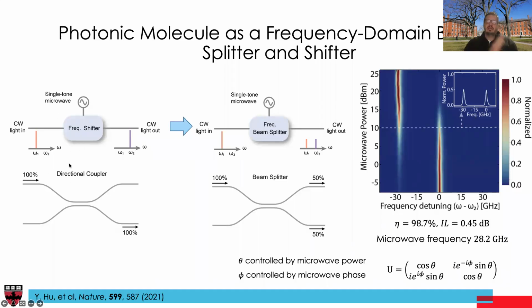If you're interested just in the single sideband modulation, okay, so now you believe us, we can do single sideband modulation or frequency shifting by the amount of original splitting between two resonators, let's say 12 gig, or in this case 30 gig. But what if I want to do more? If I have light at one frequency, I want to shift, let's say, 120 gigahertz, not 30 gigahertz. Well, I could make the system that has 120 gig splitting, but then I need to use a 120 gig RF drive, which is quite pricey.